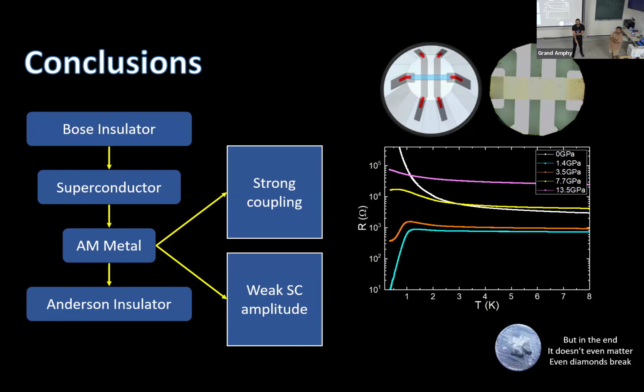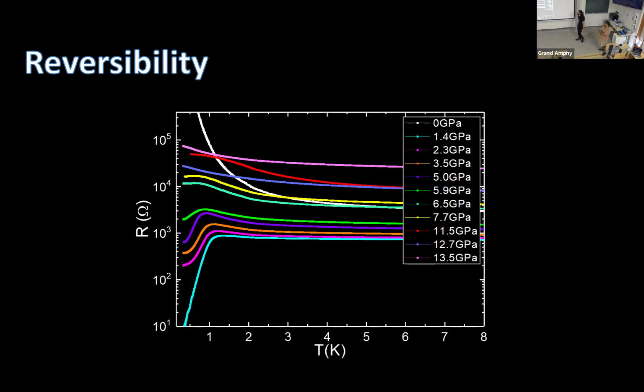Then I have a question also, which is about reversibility of the measurements. Indium oxide very easily crystallizes in many situations. If you go to 60 degrees Celsius, if you irradiate with X-ray, if you make just simple X-ray characterization, or even E-beam lithography, you can change the material. How can we know that the pressure is not changing the structure and crystallizing or making something? Are you sure you come back to the amorphous initial state?